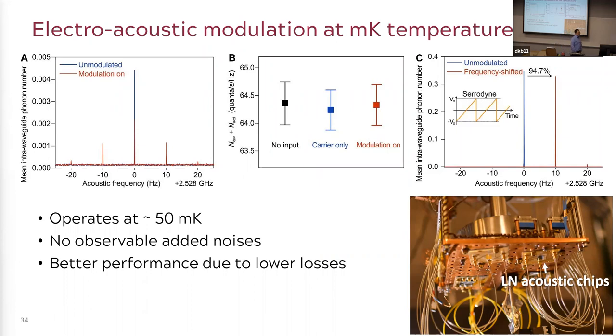The other important thing for quantum applications is noise. Does our modulation add more noise? If it's very noisy, it's useless. So we measured and compared the noise level. You can see the noise level is about 64 quanta per second per hertz. This is mainly due to the readout circuits of our quantum system. If you compare the numbers between no input, just the system output, and sending the acoustic waves, or turning the modulation on and off, you can conclude there's no significant noise being added to this system. So it's a good modulation, a quantum compatible modulation. And for sure, we can also do this frequency shifting at low temperature with even better performance because the loss at low temperature is much less.